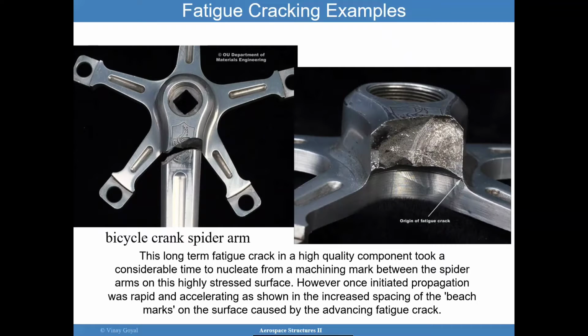It was not necessarily a stress concentration, but a machining mark, and it was highly stressed at the surface. However, once initiation occurred, it was quite rapid, and it accelerated, and you will see these beach marks that we'll be talking about later on. And then you have the ductile failure, or the sudden failure, in the remaining net section.